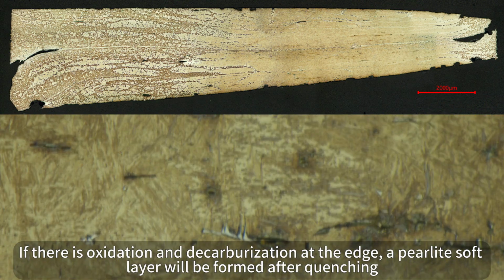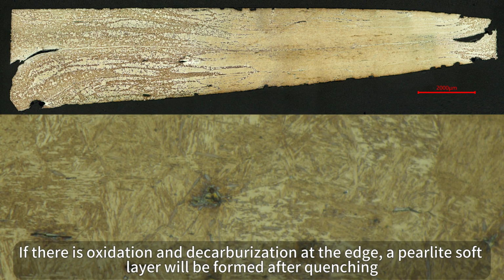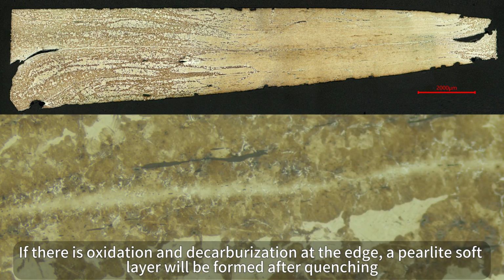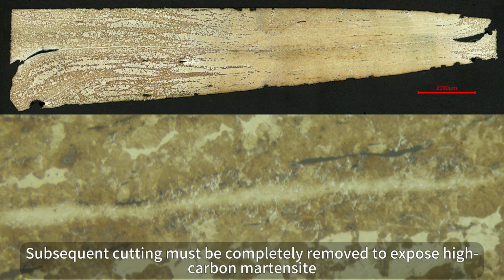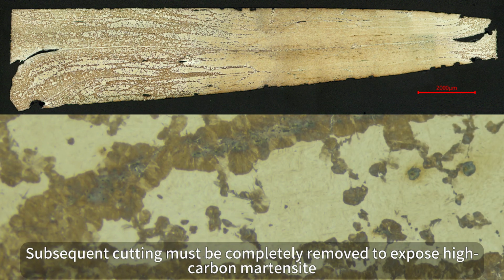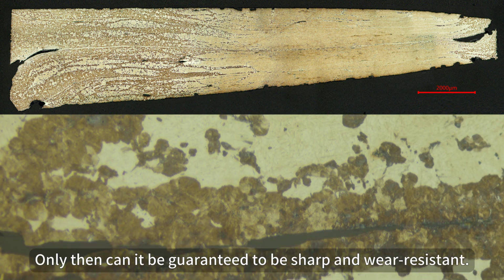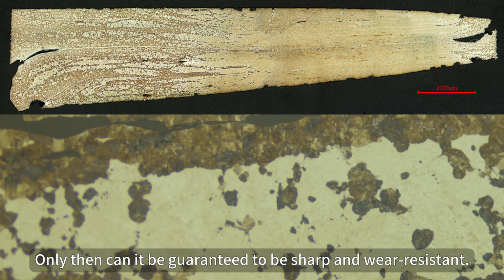If there is oxidation and decarburization at the edge, a pearlite soft layer will be formed after quenching. Subsequent cutting must completely remove it to expose high-carbon martensite. Only then can it be guaranteed to be sharp and wear-resistant.